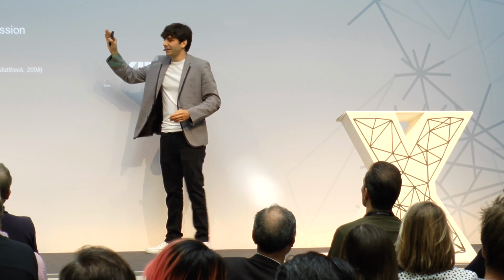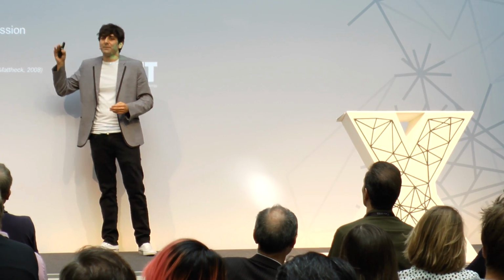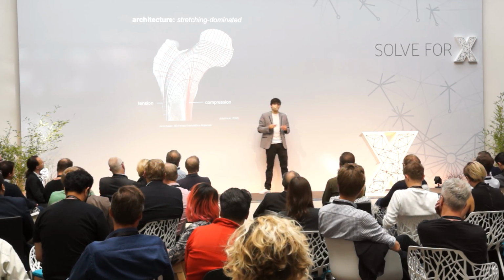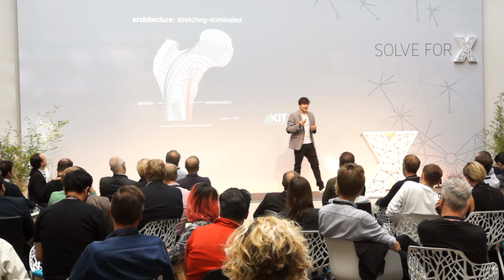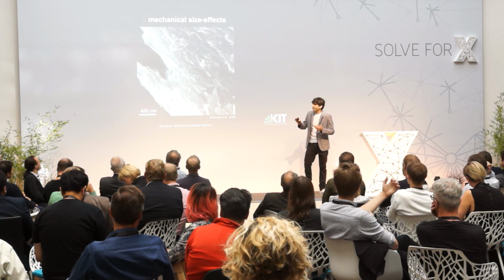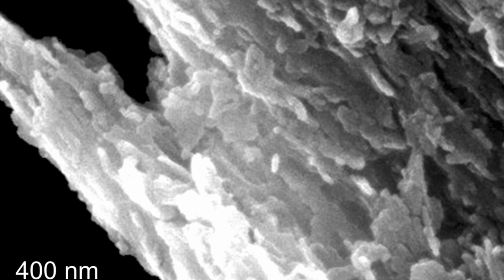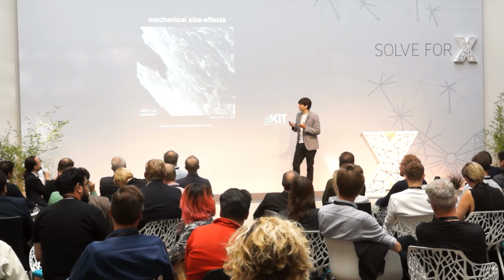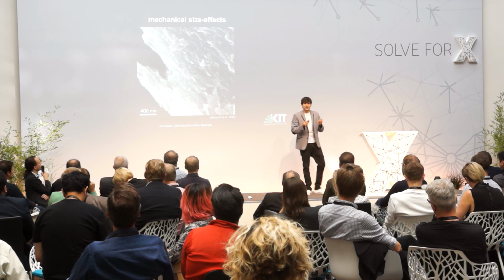And that bone over here has not only an optimized architecture, but is also structured hierarchically. The lowest level of hierarchy, which you can see here, actually consists of nanometer-thin ceramic-like platelets. And by this nanostructuring, a mechanical size effect in the fracture strength can be exploited.